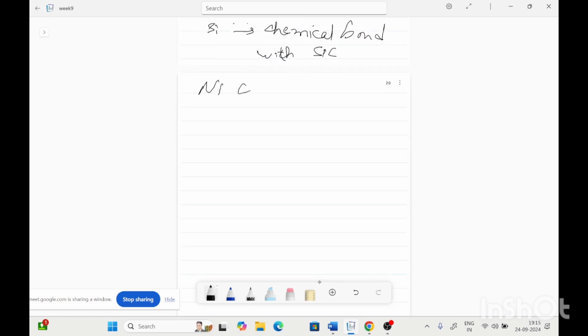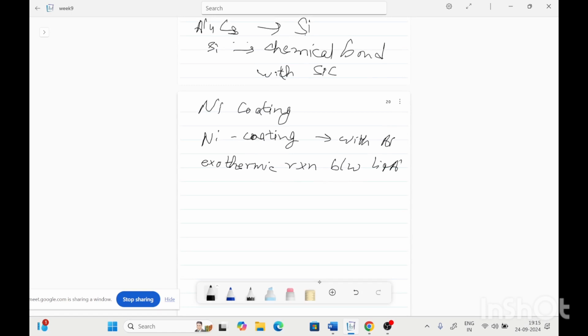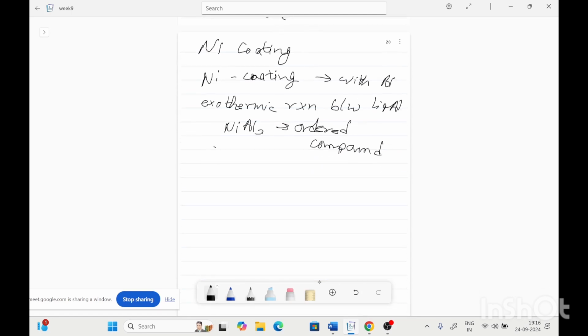Next is the nickel coating. So how does nickel coating enable good wetting? So as the nickel coated ceramic particles are added, it will react, and the reaction is exothermic. Nickel will react with aluminium. So this is an exothermic reaction between liquid aluminium and nickel, and after the reaction it forms NiAl3, which is an ordered compound. So the ordered compound has less interfacial energy.